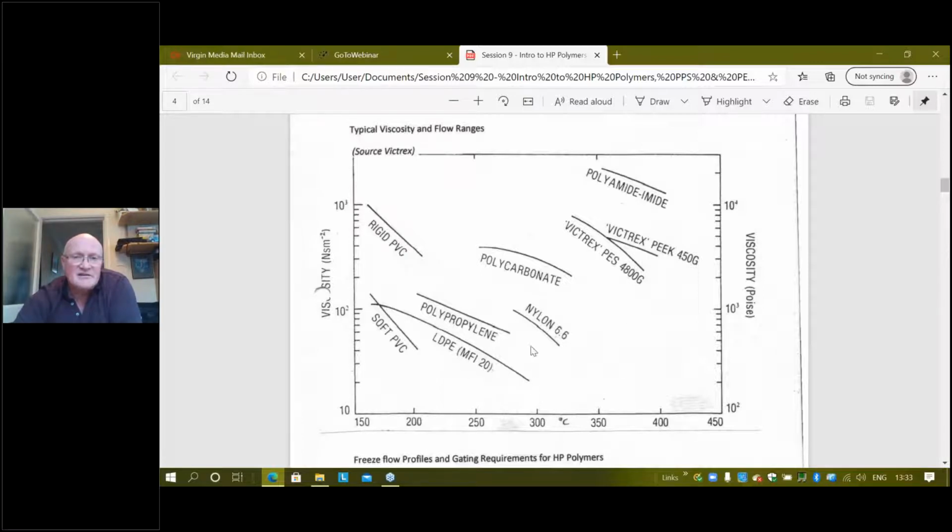Nylon 6,6 again, you can see unfilled nylon 6,6, the best flow really with control for the setter is bang in the middle of the curve. By dropping the temperature by a good 30 degrees, we'll drop that to around 270 degrees, and the viscosity has increased quite markedly, and that gives you a lot more control over the polymer during processing. Whereas if we operate too far down the end of the curve with nylon, it's too liquid and too close to degradation. And the forerunner of degradation is a drop off in viscosity. The viscosity decreases as the polymer starts to degrade, as the molecular weight starts to shorten, so the polymer flows easier. So I see a lot of setters running nylon often too hot.